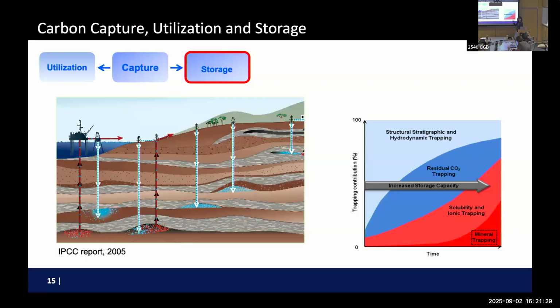This is a very famous schematic diagram from Sally Benson at Stanford. She said that if you inject 150 atmospheric pressure pure CO2 underground, which is supercritical CO2, this is what's going to happen. First, there will be a cap rock so that it stays as a 150 atmosphere high pressure CO2 plume, and it slowly goes into the pores, replacing whatever is in the pores. And then if there's water, you start to dissolve into that water and start to depressurize. And only if there's a mineral which can react, you start to make something like limestone. So this is a four-step process.